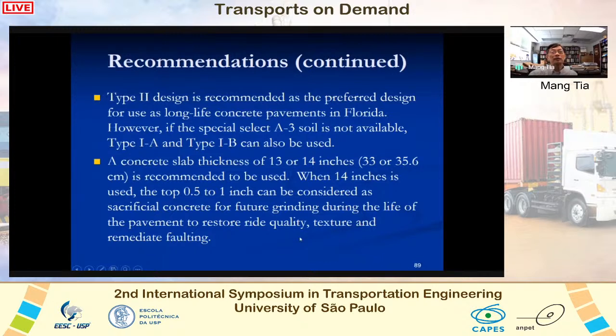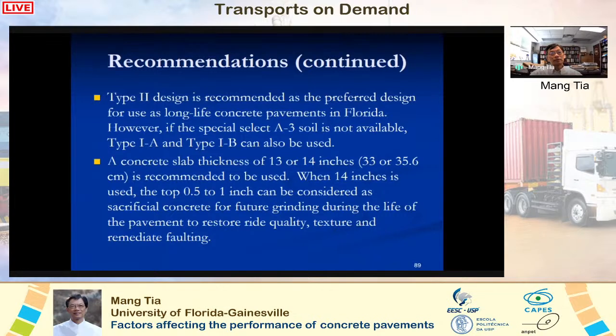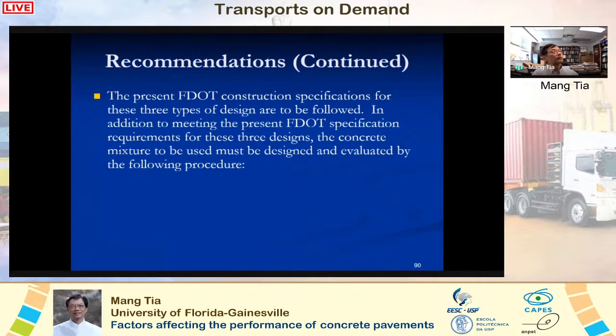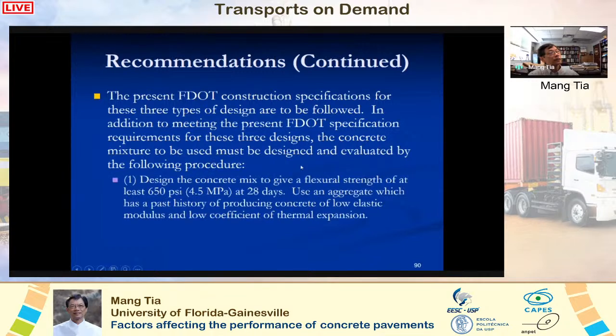Okay, after many years, concrete pavement tends to have some faulting, and we can grind it and restore its rideability. And we have the extra half an inch or 1 inch. Every time we can grind off a quarter inch, and we can do it about 2 to 4 times. The present construction specification seems to be adequate. We just need to design the concrete mixtures accordingly.